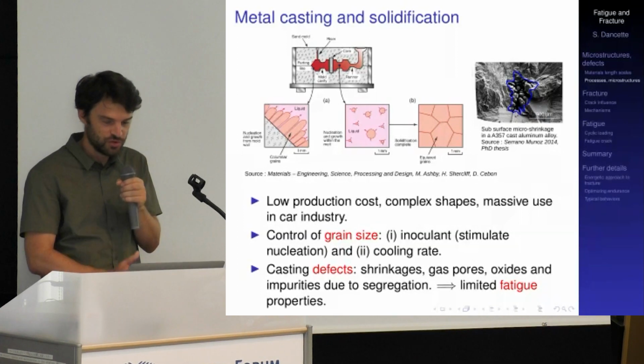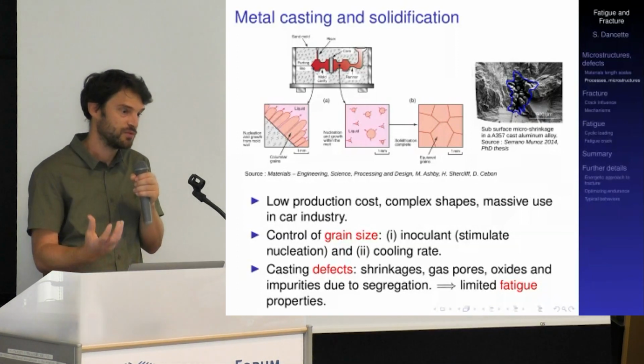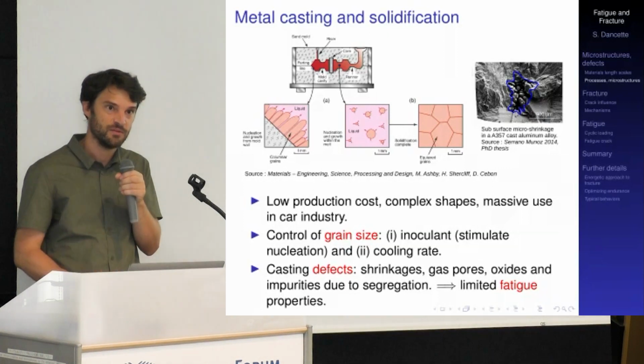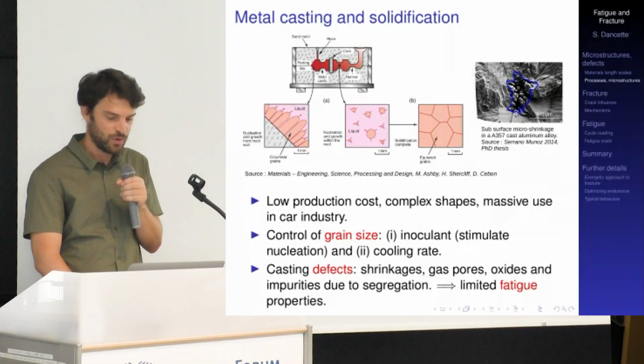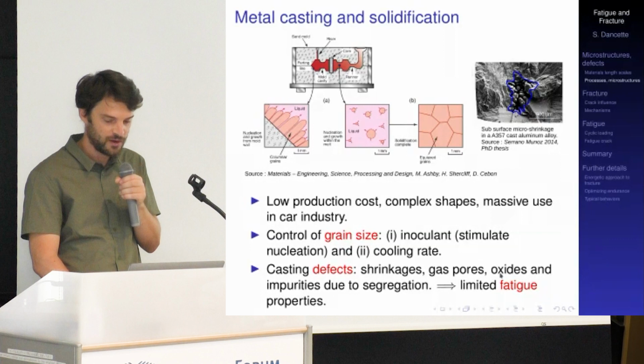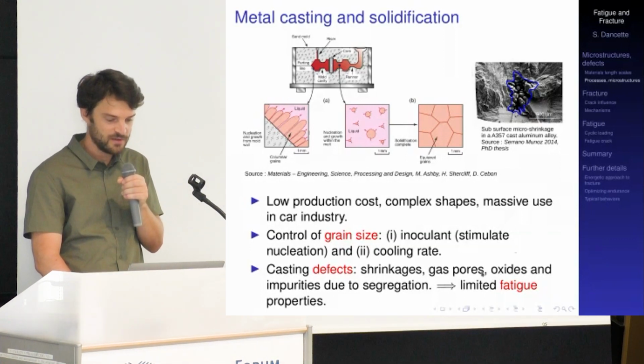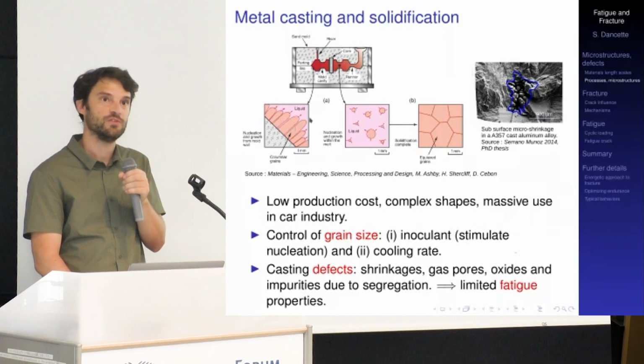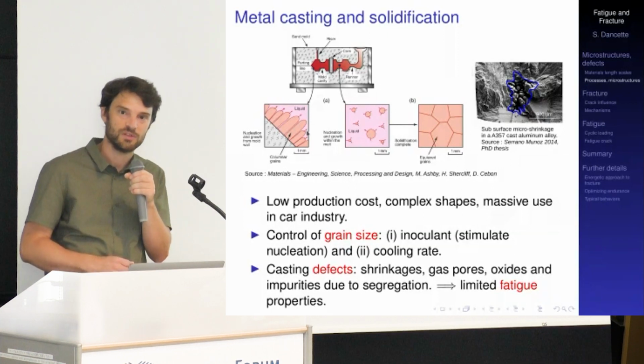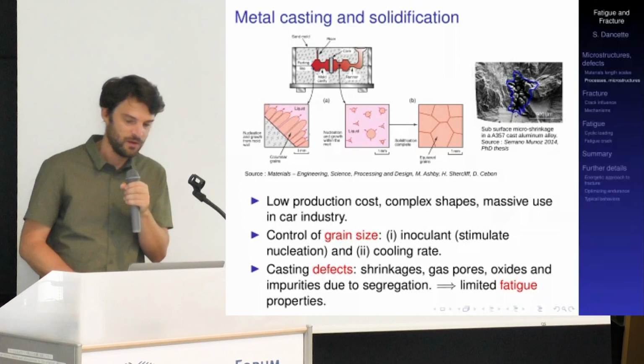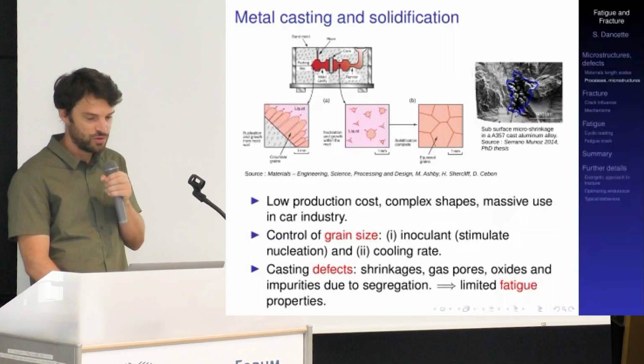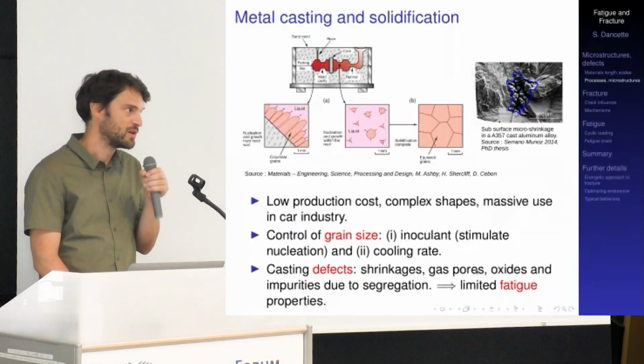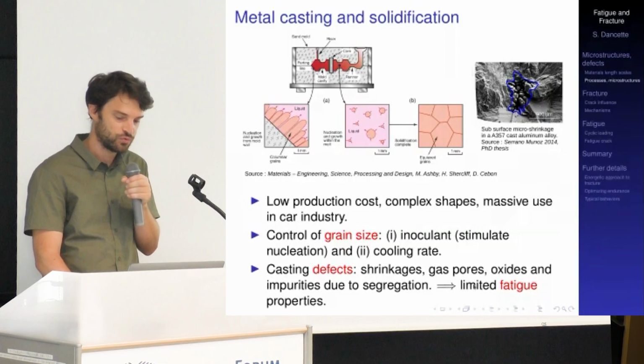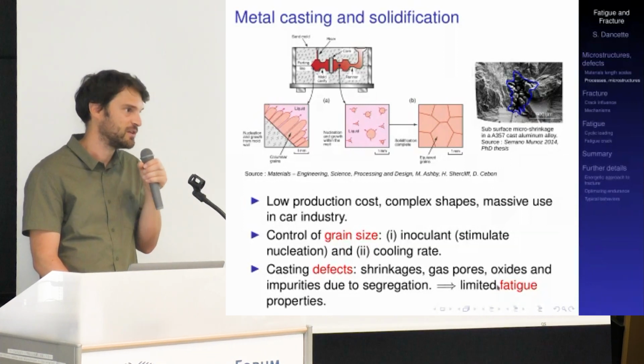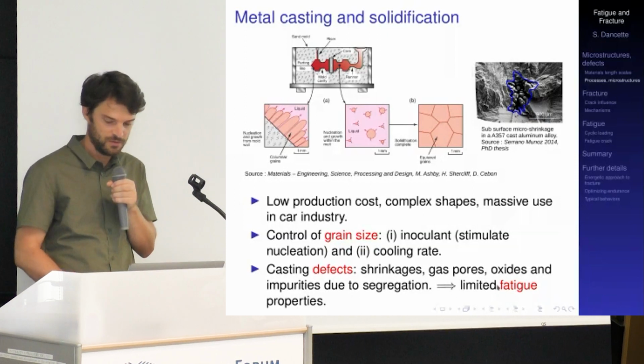Okay, so casting defects can range from these kinds of shrinkages, micro shrinkages, but it can also be just gas pores, gas that was trapped in the liquid and trapped during solidifications. But you can also find during this solidification process a lot of oxides and impurities that tend to migrate on the grain boundaries during the solidification, depending on the chemical composition of the metal. So all of these are potential defects that will most likely have a rather strong impact on the fatigue properties of the material.